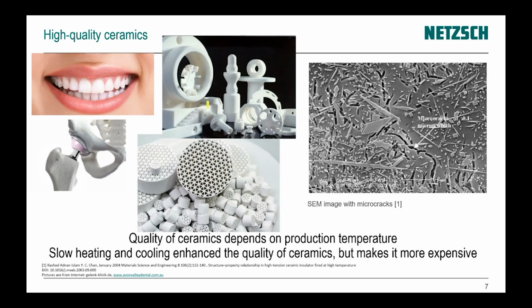If we produce ceramics, for example, medical ceramics, high-tech ceramics, then the quality must be high. Sometimes if we use the microscope in order to see what is inside ceramics, then we see the cracks. And these cracks show us how high the quality of ceramics is. We would like to have the highest quality and to avoid the microcracks if possible. In this case, we must take into account the heating rate during our production. So if everything goes slow, then the quality is higher and we have fewer microcracks.